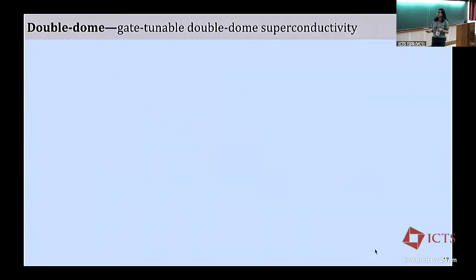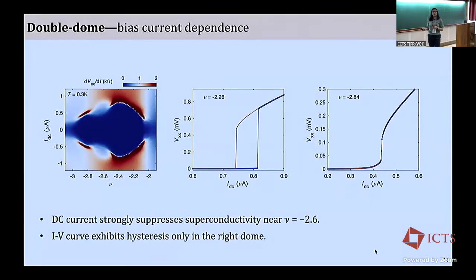And we have found that when these devices are very good, we see superconductivity in every twisted trilayer we make, no matter which angle, between 1.3 and 1.6 degrees. But only when we are at the magic angle do we see this kind of behavior. So you really need a high quality device. Yeah, this is for sure.